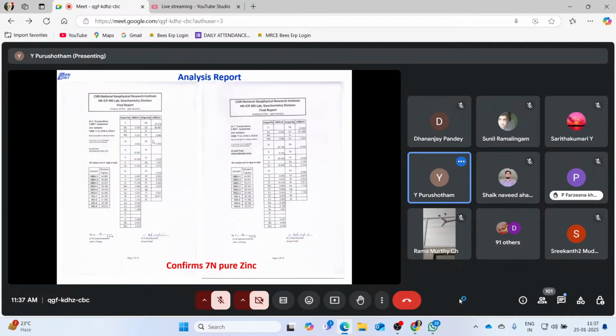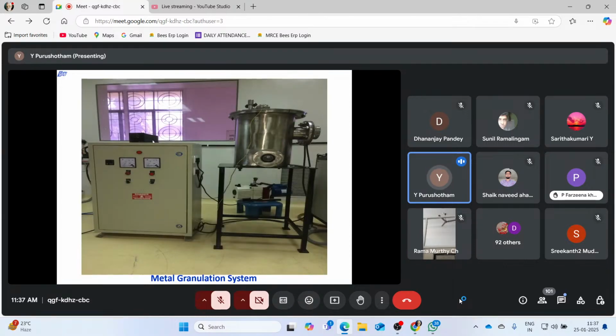And this ingot has to be converted into granules. For this, we designed a granulation system. Another advantage of our technology is that whatever process equipment we used was designed and fabricated indigenously. So here, this is a metal granulation system, a furnace cum retort. Inside, there is a graphite crucible with an orifice, and this zone refined ingot is loaded in the graphite crucible. After reaching the melting point, manually we used to open the orifice, and it used to come down.